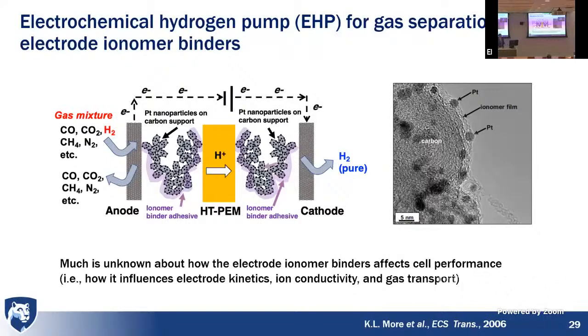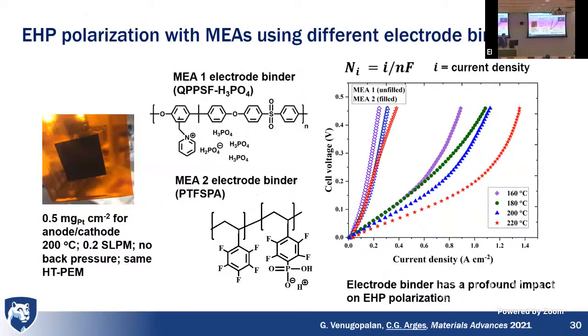How does it affect electrode kinetics and gas transport? And to illustrate this point a little bit further, I took my same membrane, same catalyst type, same catalyst loading, same cell temperature, same flow rate, same conditions, and I changed the glue from this acid-doped polycation to this phosphonic acid ionomer. So this acid now, this phosphonic acid has been put on the polymer. This has no liquid acid.